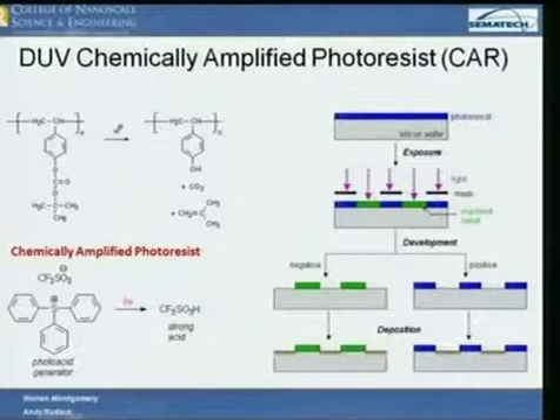The acid that was used for this is right here. It's called triphenylsulfonium triflate. Very strong acid, very strong. And the reason why it absorbs so much is these rings catch the light, generate the triflic acid, which goes off and attacks this group, cleaves these, out go those gases, generates that, developer comes in, cleans it out.